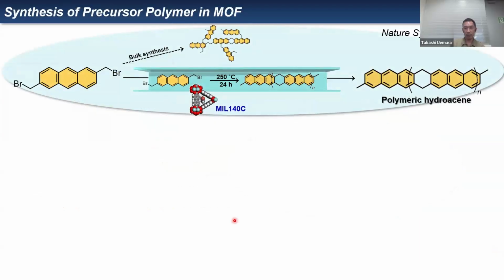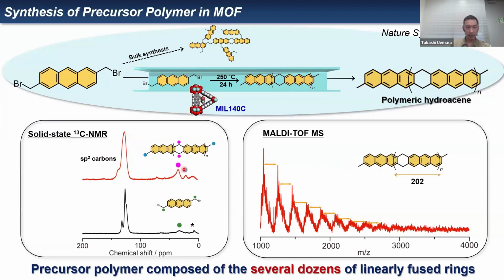So we tried to synthesize polyacene for the first time. Here we perform the polymerization of this monomer in the 1D channel of this MOF. In case of bulk polymerization of this monomer, cross-linked and insoluble carbon was obtained. But if we carry out this reaction in this 1D channel, we could obtain this polymeric hydroacene in good yield. Then we performed the characterization, and solid-state NMR shows the formation of this precursor polymer. And MALDI mass spectroscopy shows the precursor polymer composed of several dozens of linearly fused ring structures. So now we could prepare very long precursor polymers.